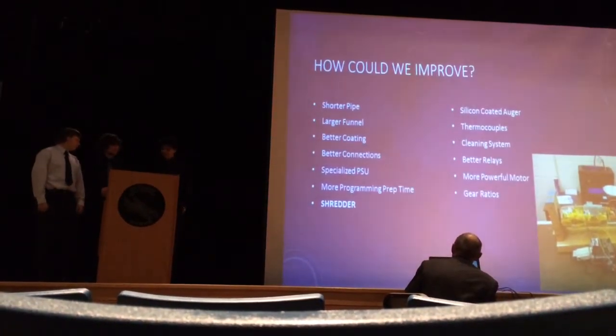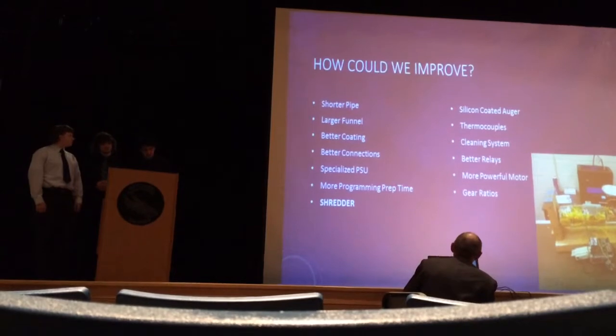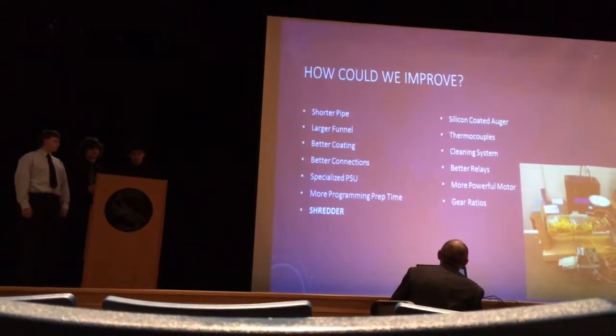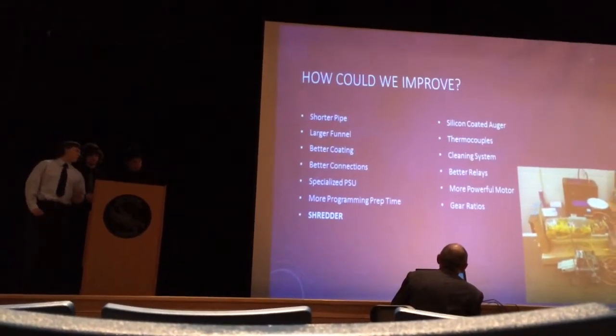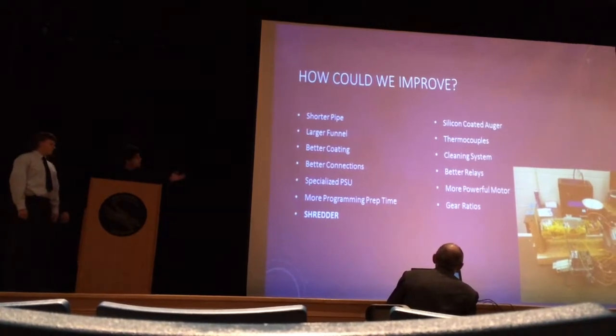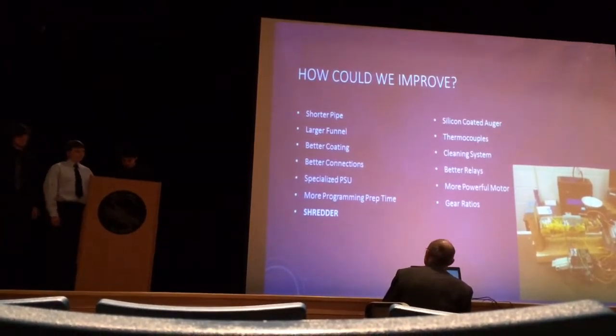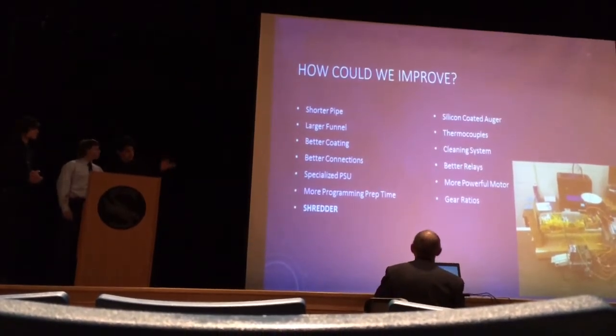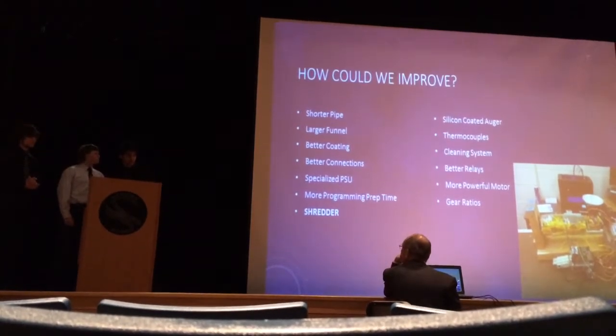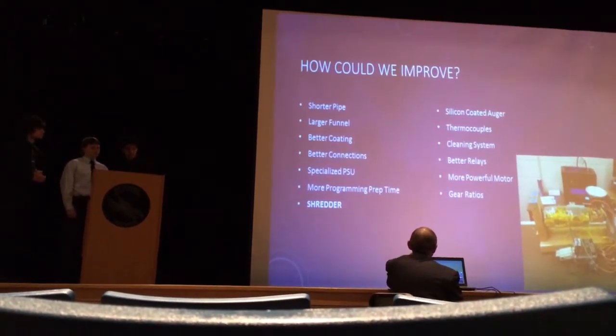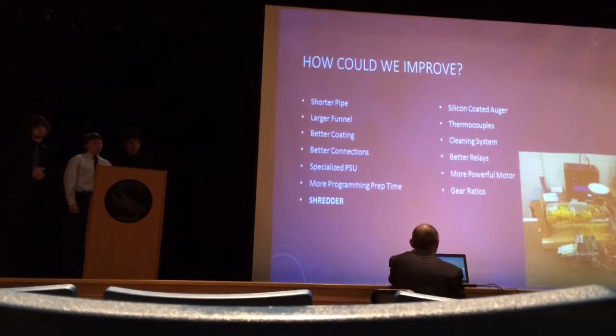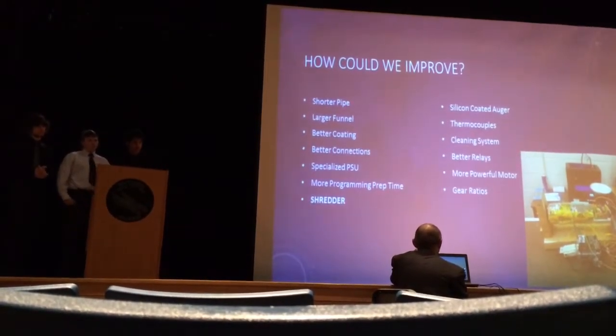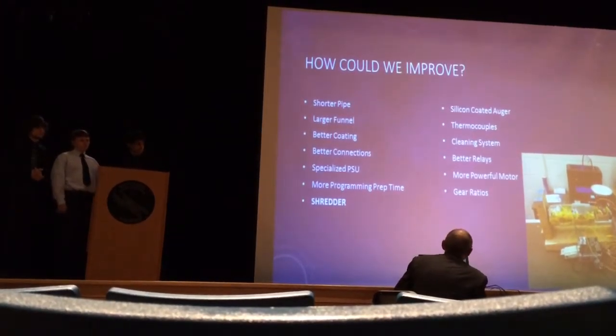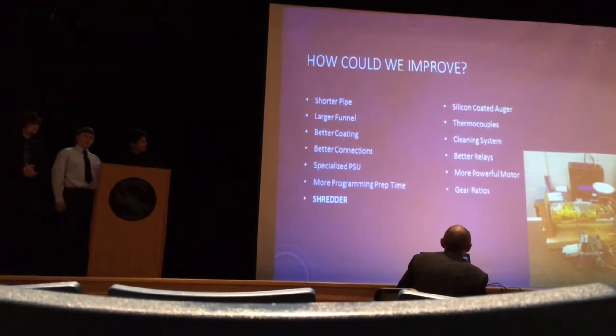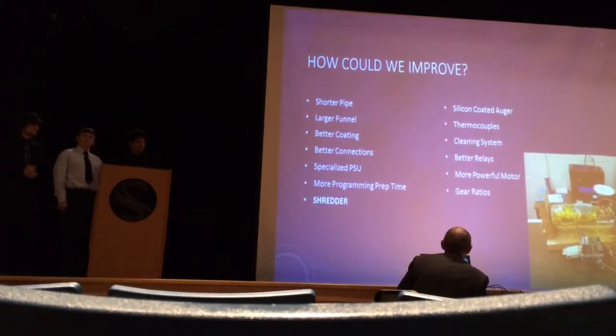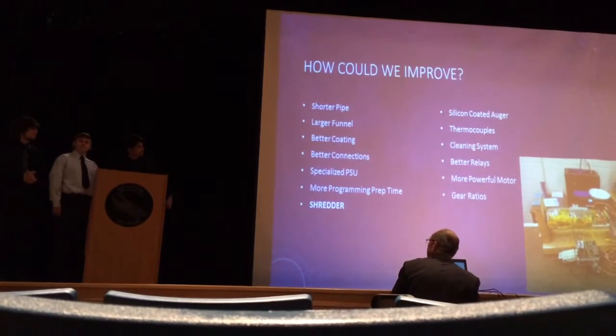Okay. So, because of the weather and because of not enough time, we did not have enough time to finish the product. But these are some things that we could improve on, such as mainly a shorter pipe to fix the problem with the auger, and the shorter pipe will allow for a lower thermal mass, meaning it'll be easier to heat up and cool down. So if something goes wrong with the system, you can react to it faster than right now.